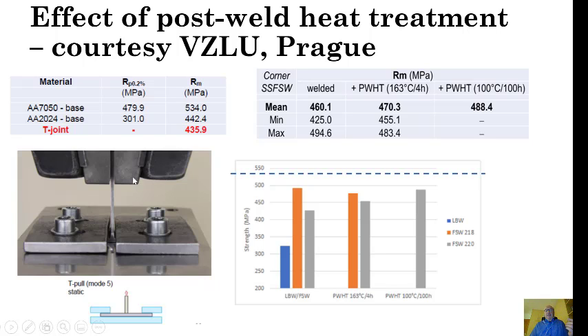This is one test. There were several other tests run. This is the T-pull test in the 7050 side. You can see that the joint has fairly good strength, ultimate tensile in megapascal relative to the two base metals. 7050 was 534 and 2024 was 442. So when we did more weld structures and did some post-weld heat treatment, notice that from 460 the strength increased by about 5% to 488, especially with this particular treatment that would not cause any problems to the structure.